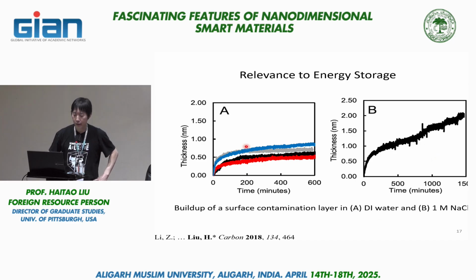So if you look at the diagram on the left, there are 4 different traces of data collected, and they are measured in DI water or nanopure water. So this is supposedly the best water, the purest water you can get in the research lab. But still, in all the cases, we find accumulation of some material within about, I would say, 1 hour. And it plateaus at about half a nanometer. So this is a very similar behavior we saw in the graphite in air experiment, except in this case it's in water, and it's in the nanopure water, supposedly very clean water, but still you have this accumulation of some stuff on the surface.